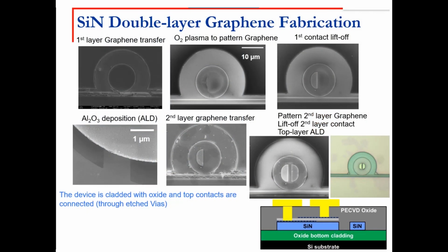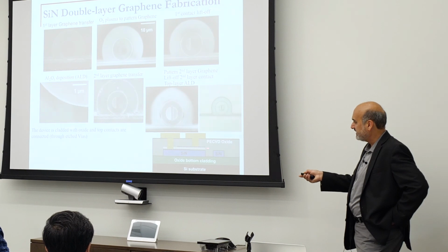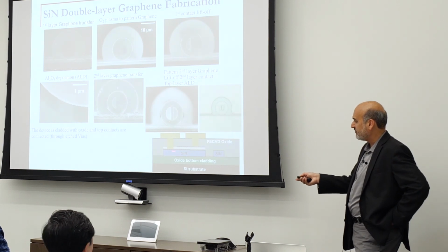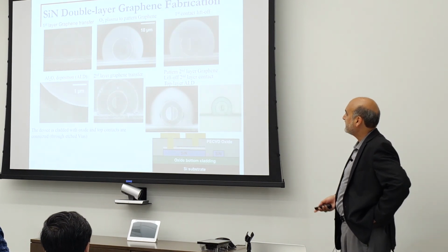These are the very high speed devices that we have envisioned using two layers of graphene on top of nitride. So that's the same capacitor we talked about in silicon. The only difference is that we take advantage of the very low resistance of graphene in order to bring the speed high.